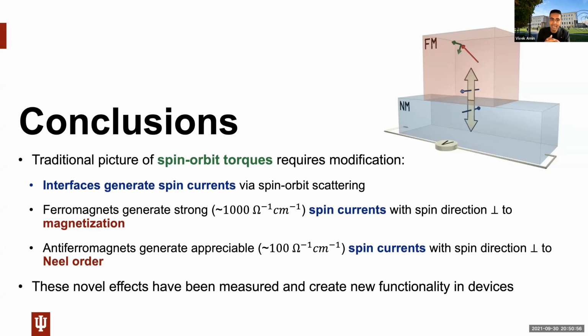The other thing is that just because something has what we think of traditionally as low spin orbit coupling in terms of the splitting of the bands, it doesn't mean the resulting effects are going to be small. So I had shown before when we had calculated the interface generated spin currents at a cobalt copper interface. Copper has small spin orbit coupling and cobalt is not that substantial, and yet we saw a big spin current. So the point I'm trying to make is that first of all, we can't really measure the strength. And second of all, even if we could, that strength isn't necessarily telling you how strong these effects are going to be. We need spin orbit coupling, but it's not really a valid comparison between effects.